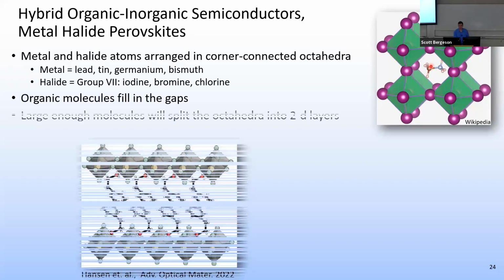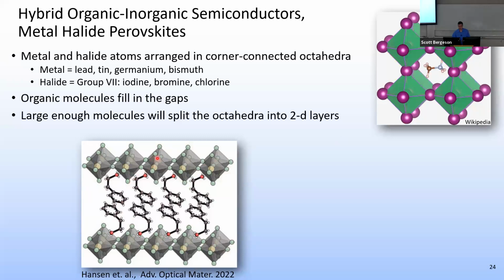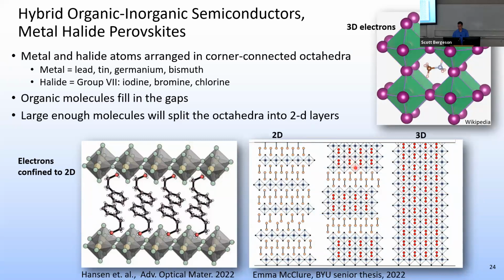But they're cool because you can use bigger molecules and split the octahedra into layers. So you get a layered structure of molecules in between, and basically a semiconductor made out of the metal and halide atoms in a sheet. The sheet is what's called a two-dimensional semiconductor, whereas this one over here is a three-dimensional semiconductor. But you can even do a mixture of big and small molecules and get something in between. So this is the two-dimensional situation over here, the three-dimensional situation over here, and then here is somewhere in between, where you start getting multiple layers of these two-dimensional sheets partnered together and then separated by organic molecules, and then multiple layers again.